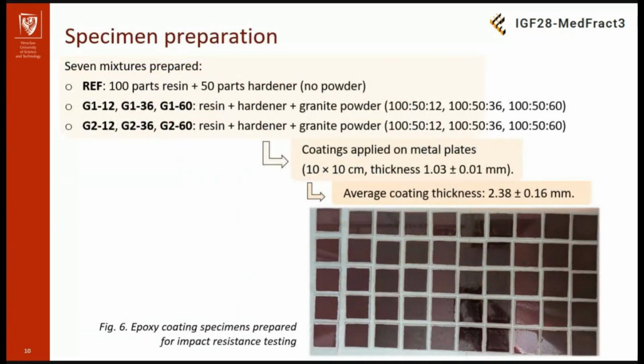I made seven mixtures: 1 reference without the powders, and 6 with powders G1 and G2. The weight ratios were 100 to 50 to 12, 100 to 50 to 36, and 100 to 50 to 60. 100 is resin, 50 is hardener, and the third number is the granite powder. I applied the coating on metal plates. The average thickness of coating was 2.4 millimeters. Here you can see all prepared specimens placed side by side.